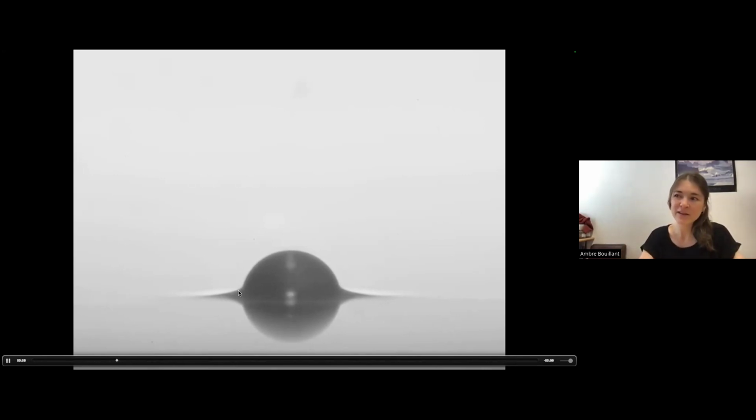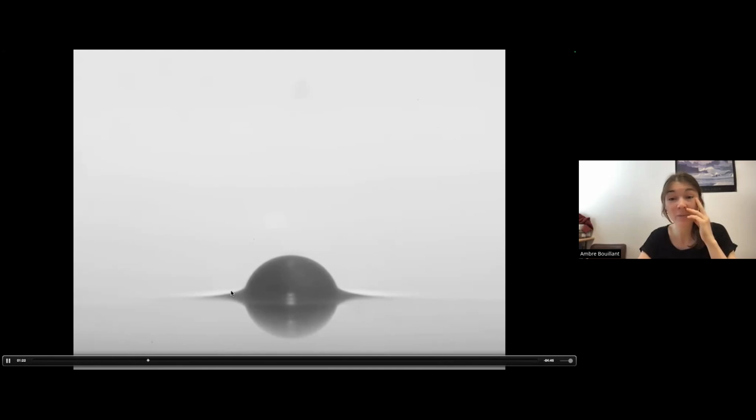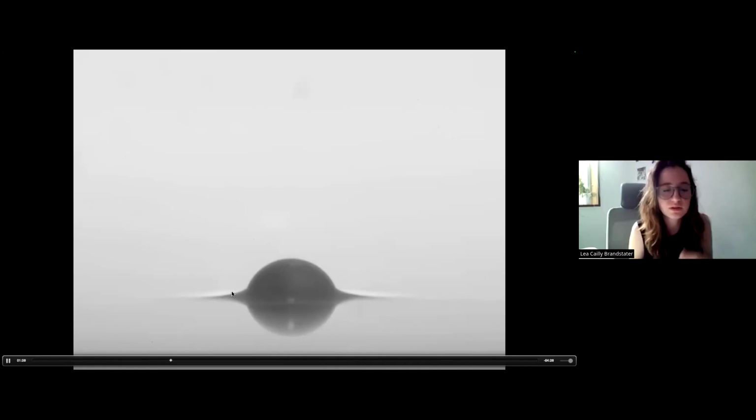But in some sense, we didn't look much into this because at the scale at which droplets nucleate and grow, the droplets are much smaller than the capillary length. Okay. Wow. So that's why they have this very strange shape, because when R is close to the elastocapillary length, you have a little ridge that is not so much developed. But here the substrate is so deformable that the drop can really sink into the gel.